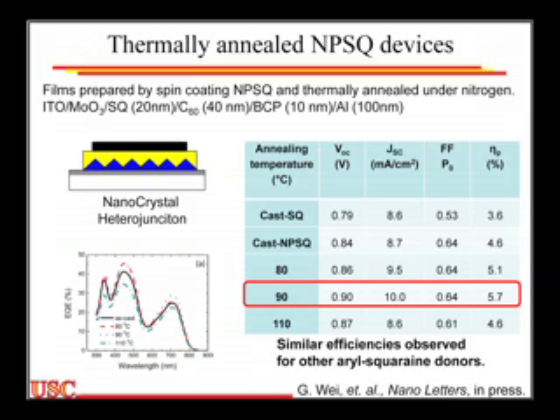And keep in mind, this is 5.7%, and I'm not collecting very many photons between 500 and about 650 nanometers or so. This is the peak of the solar spectrum, not a valley in the solar spectrum. And as we're now filling, which you'll see I have some strategies for filling that I'll talk about in a few minutes, we should be able to push this up much higher than where we are now. So we're quite enthusiastic when we saw 5.7%.